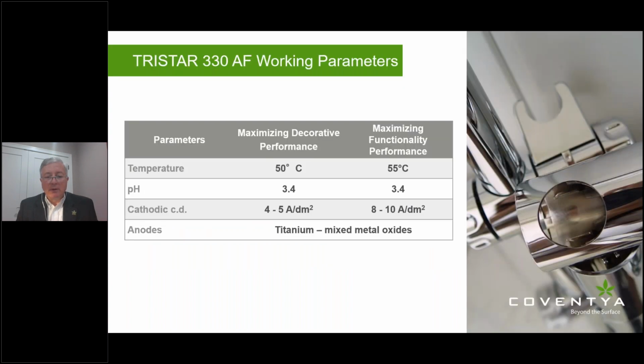Next. If we look at some of the details of the working parameters, again, one of the differences is operating temperature between the decorative and functional performance, and the pH of these systems. One of the biggest advantages of trivalent technology is a much higher pH than chrome 6, which is -1, very acidic. These are less acidic than those. But again, we operate at different current densities. We use titanium anodes with the mixed metal oxide coatings on them for this technology, and it operates very successfully under those guidelines.